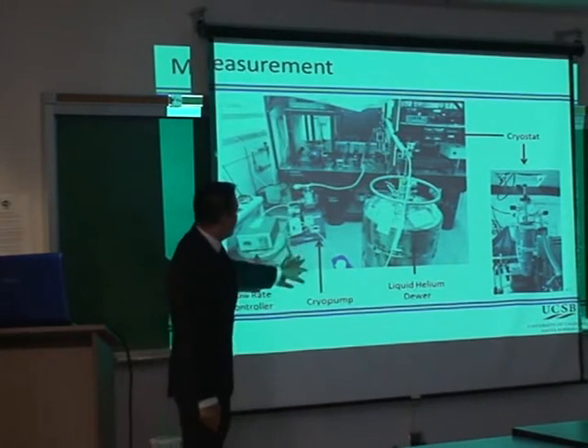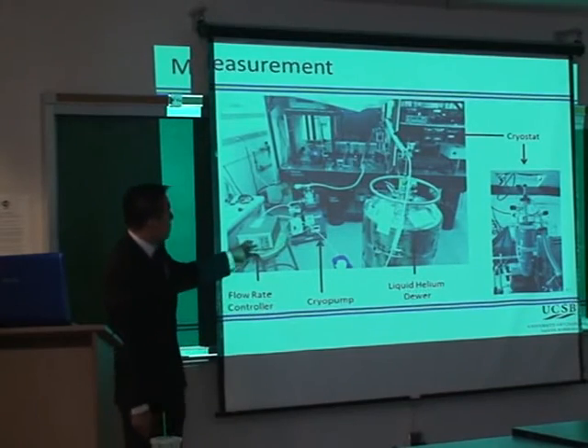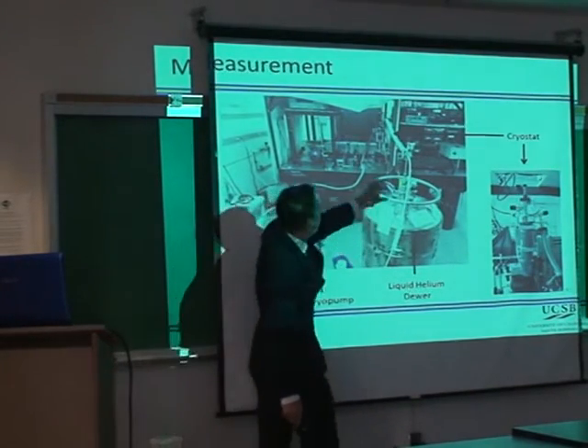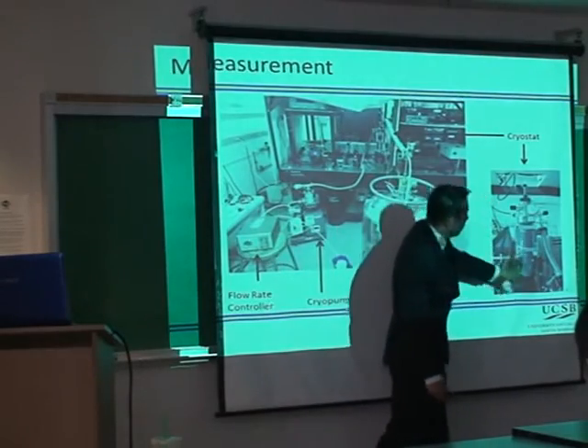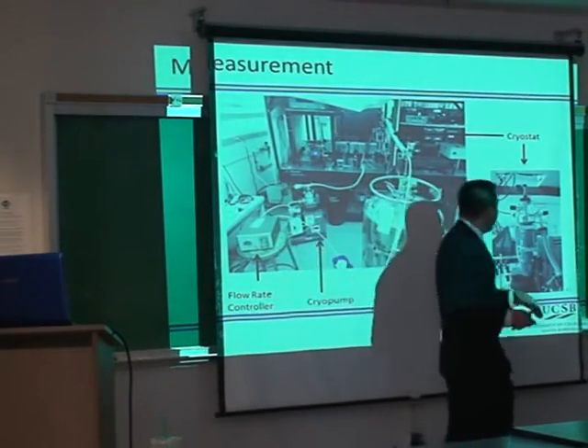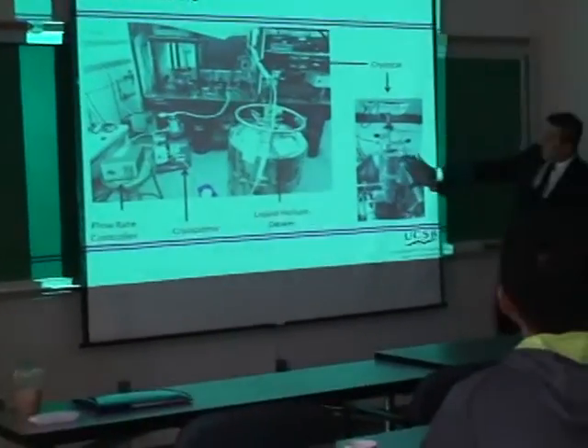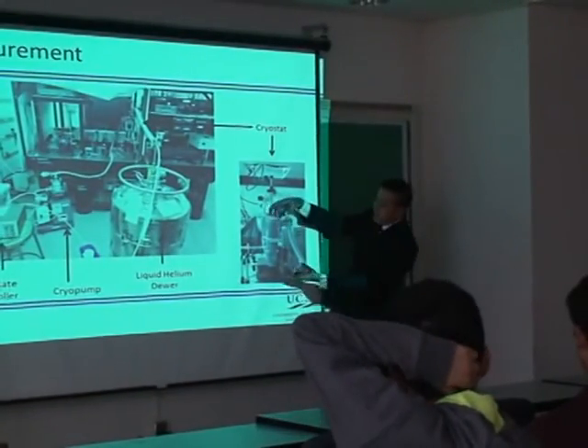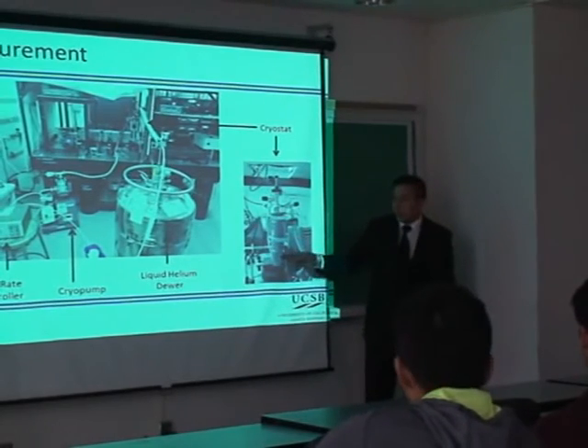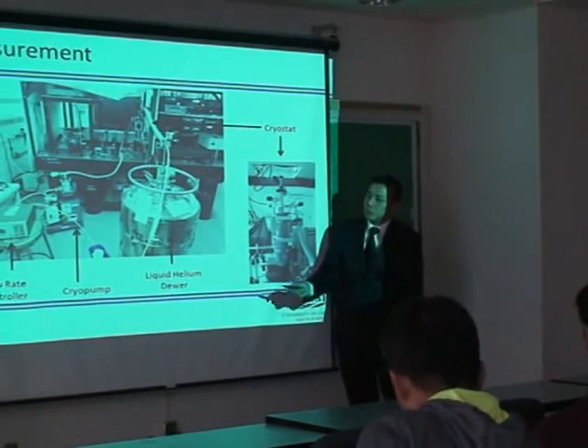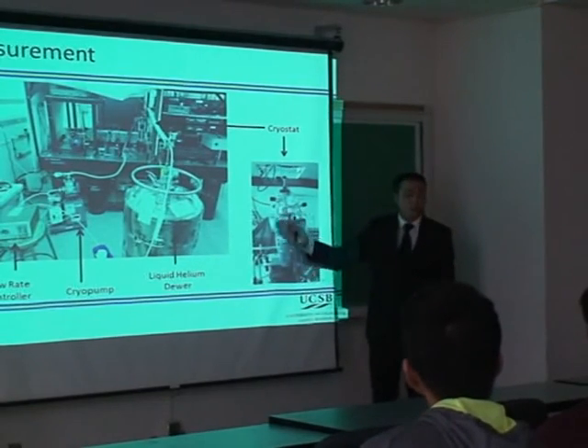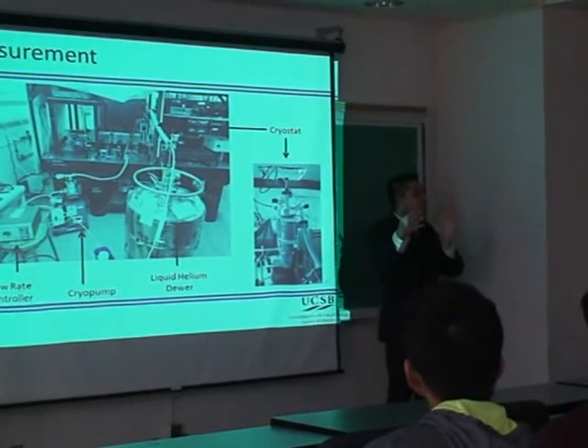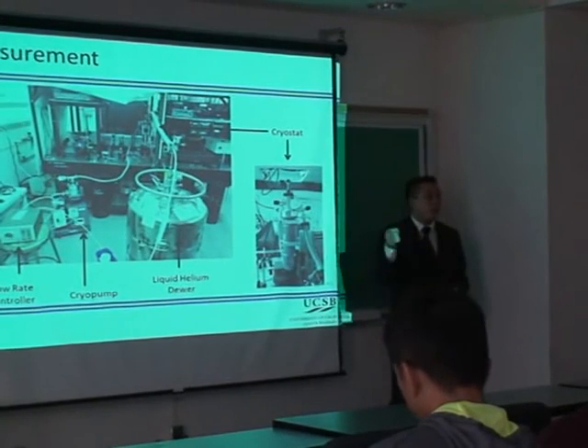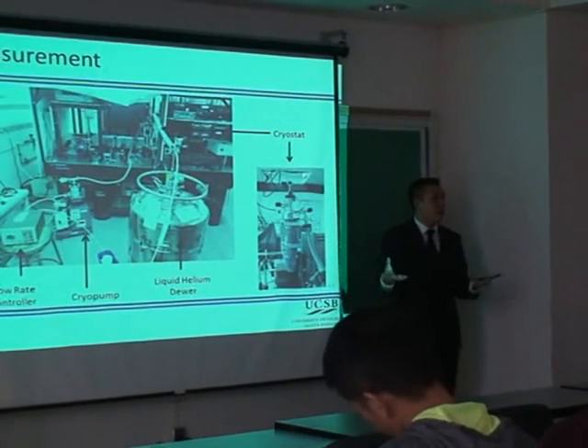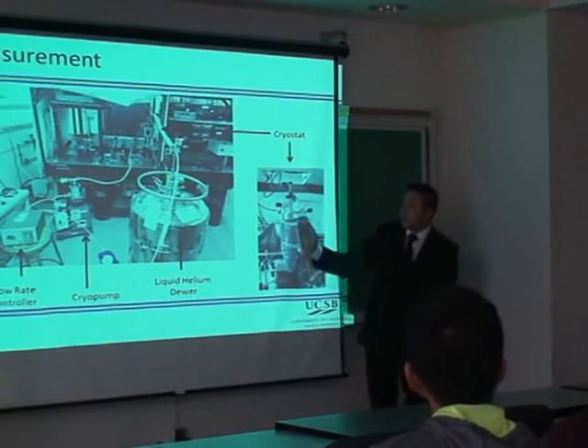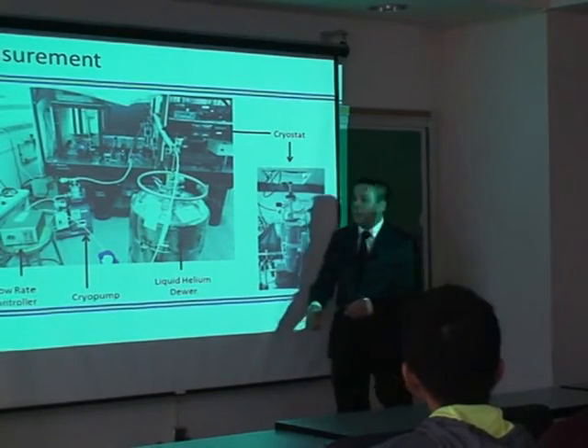What we also had here in our setup is a flow rate controller. This allowed us to manage the rate of flow into our setup so that we can control the temperature. So we could either cool it down or heat it up. And this was the cryostat, where basically we put our film in here, the 3 that I showed you, and we measured through here. What's also important is that we use a cryo pump to pump down the walls here. We actually want to create a vacuum around the walls because the inside will be very cold, 4 to 10 Kelvin at one point. And what can happen is condensation can build up if you don't have a good insulation layer around this cryostat.